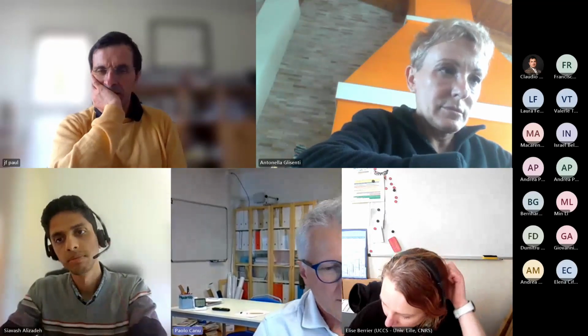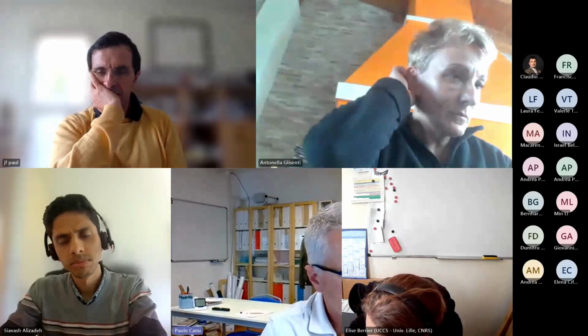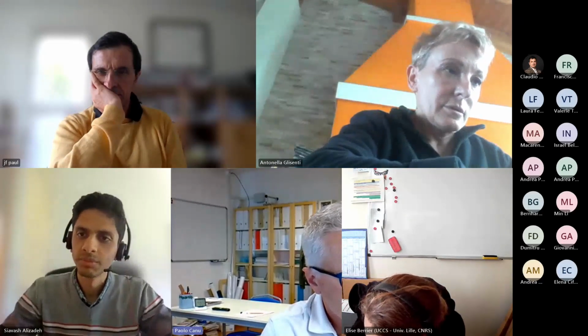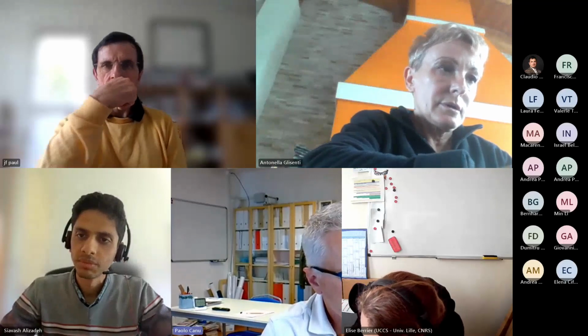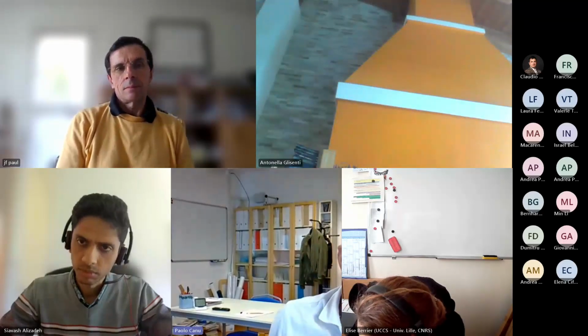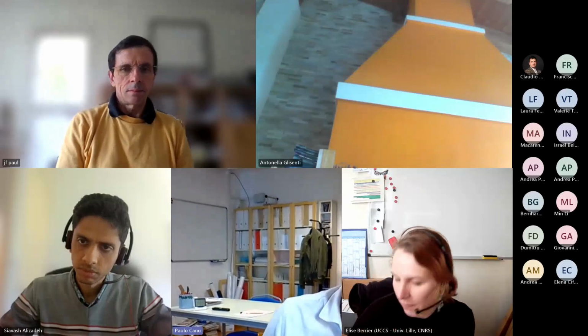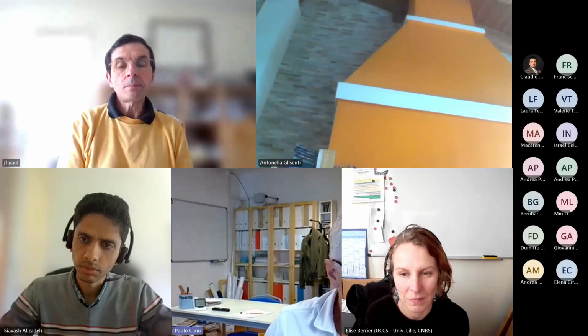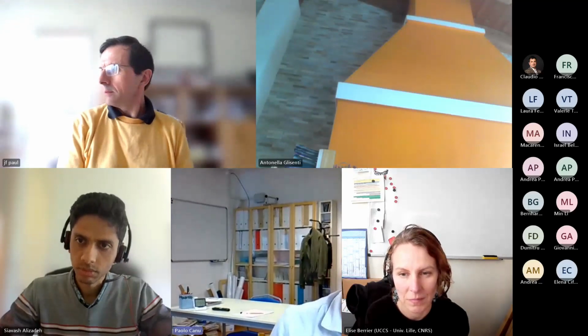That's what is tentatively done by the so-called tortuosity. You saw that I mentioned there is a tau called tortuosity, typically introduced to estimate the effective diffusivity into a porous domain. And the tortuosity is an empirical approach to describe the shape of the pore. So porosity is the amount of voids into the porous region, while the tortuosity tries to summarize how tortuous or complicated are the path of the pores. But it's quite empirical.